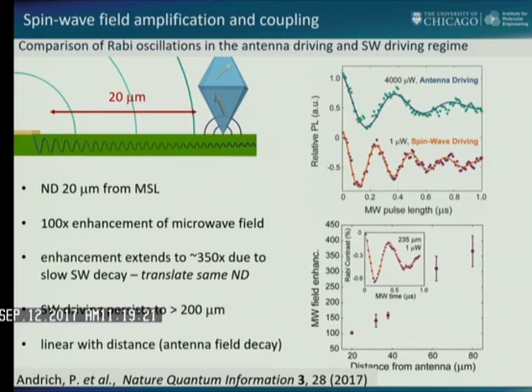And what he found is that the enhancement kept growing and growing. The signal just never dropped compared to an antenna. So when he moved, in this case, a couple of 100 microns away, which is a very big distance quantum mechanically, it worked beautifully. And this is well beyond the reach of photonics. It's well beyond the reach of traditional gating, but it works very well with magnets. So we think this is a very interesting new direction for this field, using ferromagnetism to control quantum states.